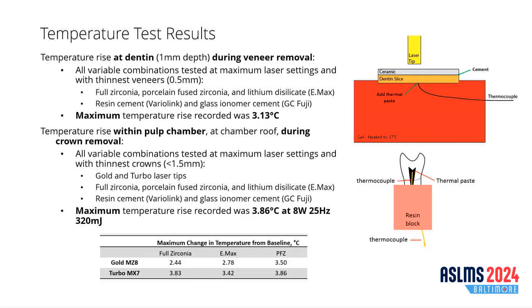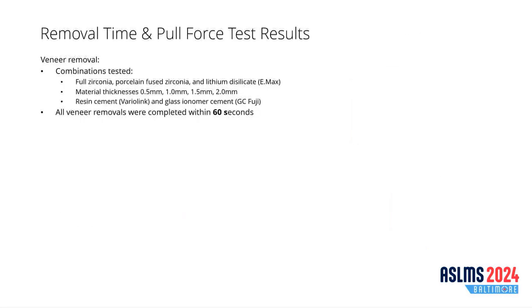We tested the thinnest crowns, of course, looking for the maximum settings with a safe temperature rise. The maximum recorded at 320 millijoules was 3.8 degrees Celsius. Of course, if you go above 320 millijoules, the temperature increases were higher. So we don't recommend going above 320 millijoules.